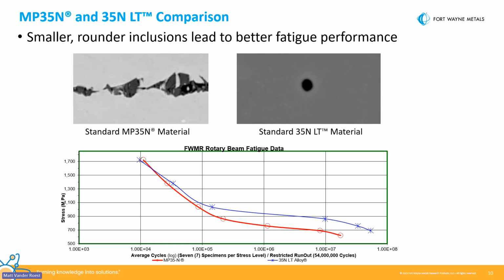So in the 80s, Fort Wayne was working with many medical device companies and trying to improve the performance of our materials. And one of the things that limited the fatigue performance of MP35N, which was an industry-leading material, was the presence of titanium nitrides and titanium inclusions in the actual melt material. So Fort Wayne worked with our industry partners as well as our supply chain to design a melt that allows us to remove a significant portion of the titanium, and thus it imparts very different properties in the fatigue life.